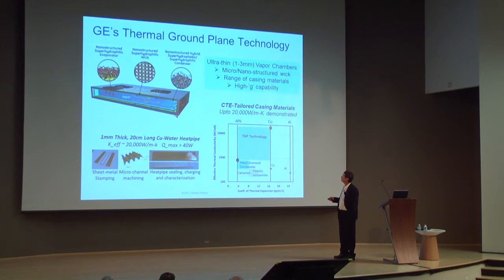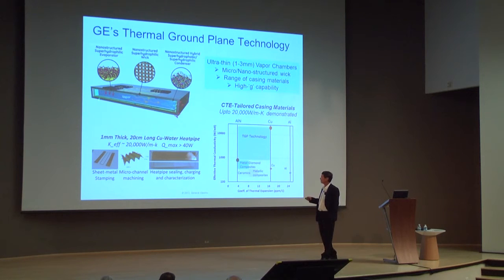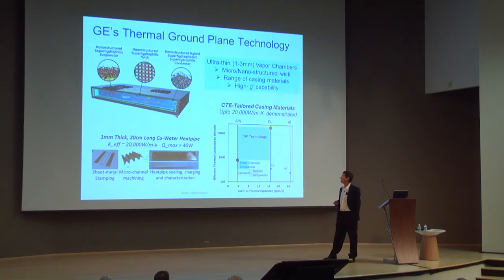Another one is what we call the thermal ground plane technology. Here, you have some very hot chips producing a lot of heat. You put them on a substrate like this, where it's got a material here that acts like a heat pipe. It gets vaporized at this end, it goes to the other end, and then you can take it out in the large area over here to some other medium, some other cooling device. So this is like a small heat pipe you can put as the substrate for electronic devices that are putting out a lot of heat. And it turns out that with this thermal ground plane technology, convection basically beats conduction. These convective techniques can beat any of the other substrates we've been able to produce, including diamond substrates.